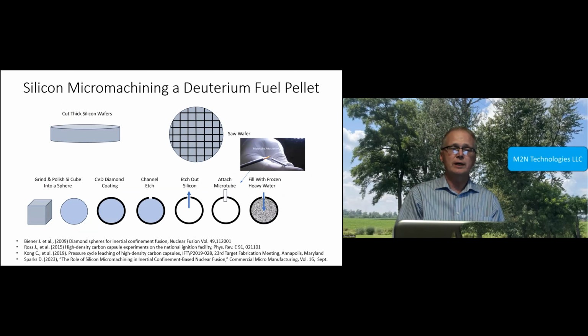So again, this shows you cutting thick wafers, dicing the wafers. Instead of having chips for an integrated circuit, you've got cubes for a sphere. You then knock off the corners, rounding them with that abrasive process. You use CVD coating to put on the shell. You've got to etch a very high aspect ratio channel, a single channel into that diamond shell, and then remove the silicon. That's a microfluidic feat, because that's a lot of material. You've got to attach that tube, which is shown in the picture. That's done manually now, so it's a very labor-intensive process.